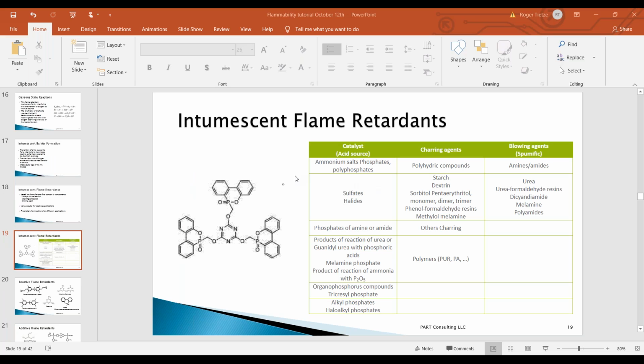So you can see here on this slide, to the left is a proprietary phosphorus melamine-based basically charring agent that has been patented. But basically, you can see all of these catalyst sources. They basically trigger off the blowing agents, which are listed. Urea is very common, formaldehyde, and various other derivatives of many of these things. Charring agents can be anything from starch to melamine, phenol formaldehyde resins, and basically any other kind of polymers that can work in this application.